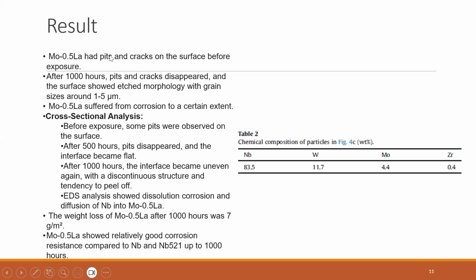molybdenum alloy had pits and cracks on the surface before exposure. After 1000 hours, pits and cracks disappeared, and the surface showed etched morphology with grain size around 1 to 5 micrometer. Molybdenum alloy suffered from corrosion to a certain extent.